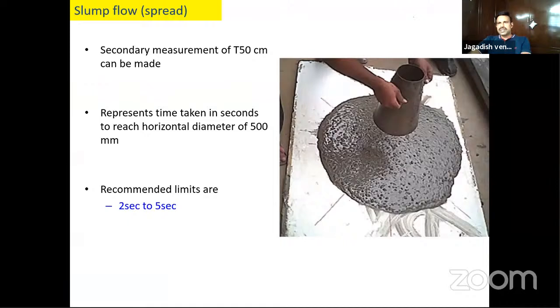There is also one more measurement we do for self-compacting concrete. That is the time taken for the concrete to reach a diameter of 500 mm. Because you know the cone size, right? The bottom is 200 mm, top is 100 mm, the height is 300 mm. So when you lift the slump cone, the 200 mm spreads. The time taken to reach from 200 mm to 500 mm, we measure that, and we call it the T50 centimeter time. It should be between 2 to 5 seconds.